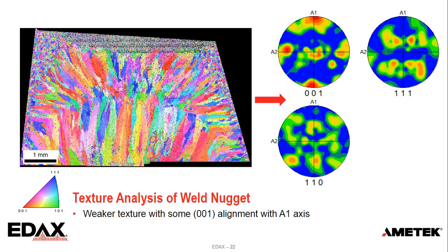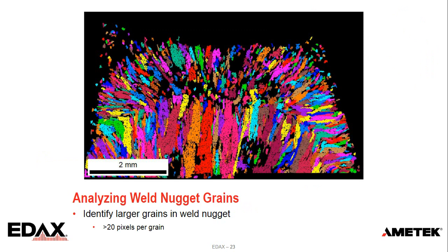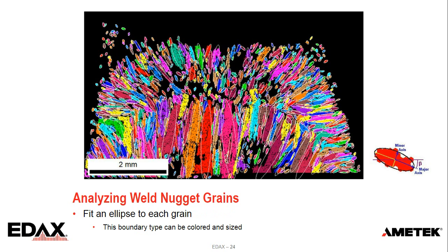Just to investigate that a little bit more, I pulled out the grains of just the weld nugget. From this crop data, I specified, show me all the grains that are larger than 20 pixels. So here's a grain map showing that. We see a lot of those elongated grains. Once I have those grains identified, I then fit an ellipse to each grain. We determine a major axis and a minor axis, and an angle between the horizontal and the major axis. I've just shown those ellipses in white to show how they fit those elongated grains.